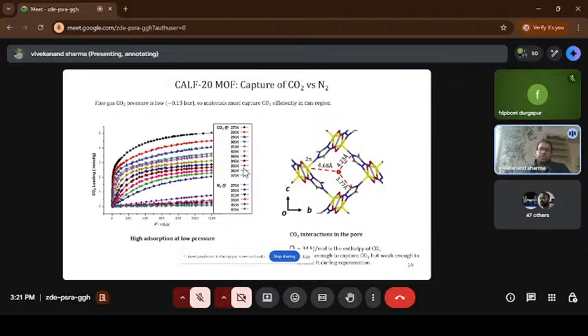So this was a very promising result, because this MOF was not capturing the nitrogen. It was capturing carbon dioxide more at the same lower pressure. So let's talk about how the CO2 exists in between the pores of this framework. Here I have shown one pore, and the red color represents a carbon dioxide molecule, which you are seeing perpendicular to my laptop screen. This gives three interaction points at a distance of 4.68 angstrom and this one. So these are the smallest interactions existing in the material that stabilize the CO2.